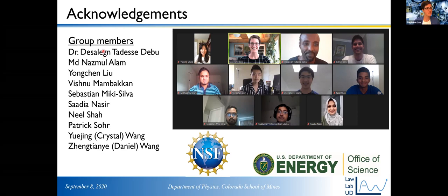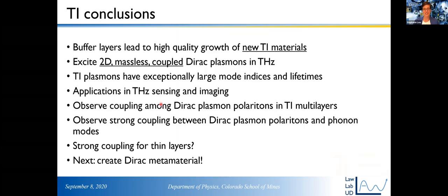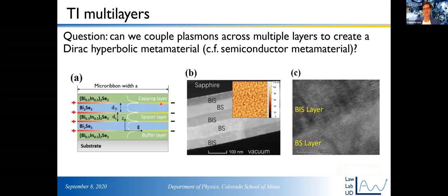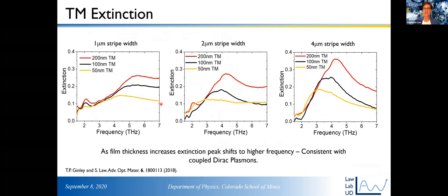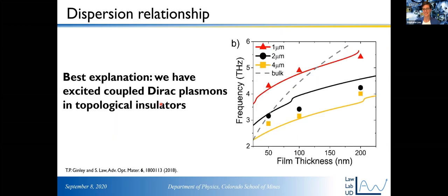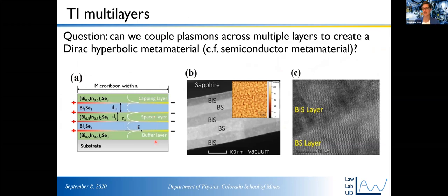So it looks like we have a question here. Since the bismuth selenide is deposited on a dielectric substrate, are the top surface and bottom surface SPPs at different frequencies? This is a really good question. This is something that we worried about quite a bit, because as you note, air has a permittivity of one, and sapphire has a permittivity of more than one. So the answer to your question is yes, they really are at slightly different frequencies. If you look at these single layers, they're at slightly different frequencies. Fortunately, you can see how wide these excitations are. It turns out the frequency difference between the top surface and the bottom surface is much smaller than the width of the excitation. And so we are still able to get the strong coupling. But what we've done with these multi-layers is just avoid that problem by encapsulating everything with bismuth indium selenide. So now everything has the same dielectric material on either side of it. But yeah, that's a very good point.